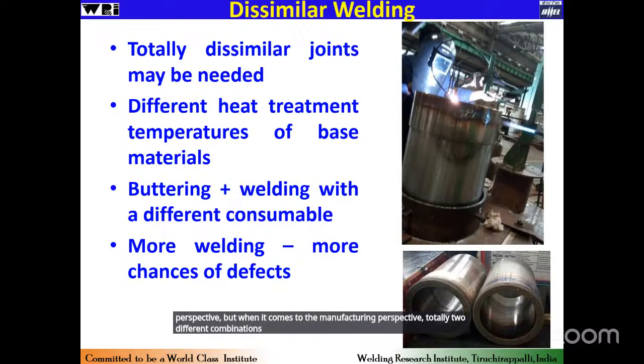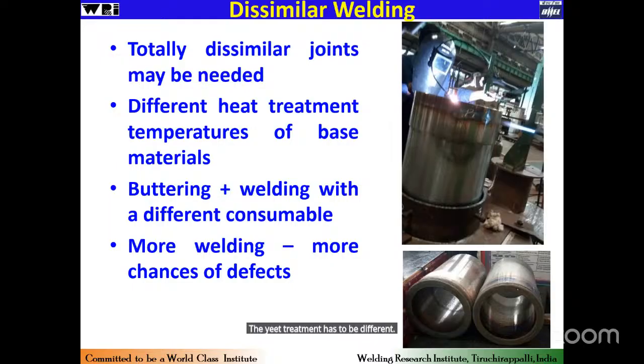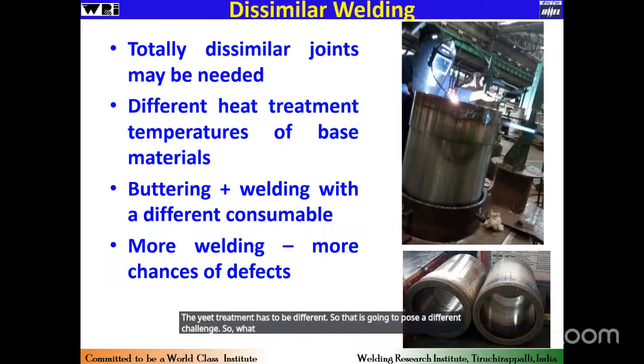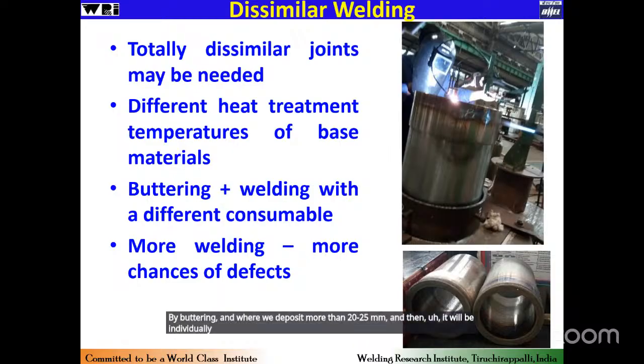When we talk about such kind of dissimilar combination, especially with the thicker sections, the heat treatment has to be different. So that is going to pose a different challenge. So what has been done is, we have to choose a consumable which will be compatible with both the grade of materials, and that consumable has to be deposited by buttering, where we deposit more than 20-25 mm, and then it will be individually heat treated according to the temperature requirement for that base material.